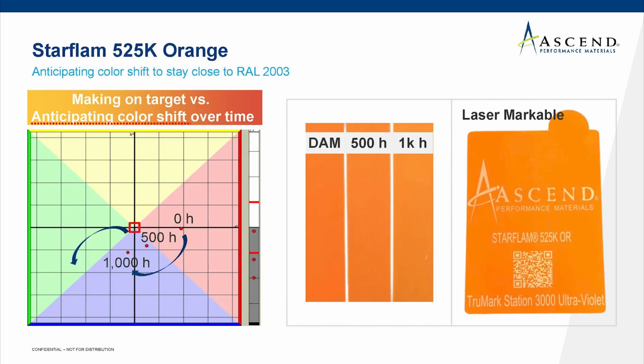And then we talked about the orange RAL 2003 that we like to target for this application. And if you look at the diagram on the left and that red square in the middle, that would represent the RAL 2003. And after aging over time, you can see that going into the green space, it would move very far from the RAL 2003. Versus if we start at a slightly shifted value and then age 500 hours to that red dot and then 1,000 hours to that red dot, we end up in a place that's closer to the targeted RAL 2003.